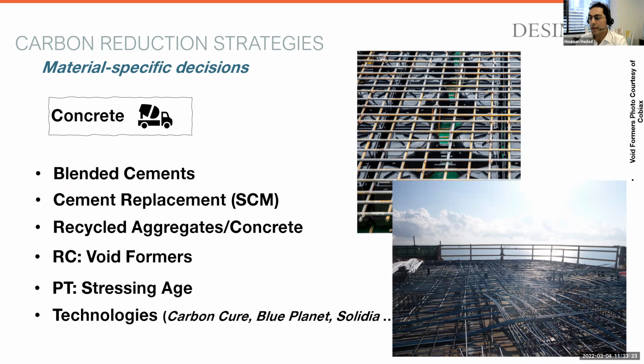Why? Because when you're adding fly ash and slag, chances are that you cannot gain early strength, 3-day, 6-day, 7-day strength in your concrete, and you have to wait a little bit longer. It's more challenging to gain early strength with a high percentage of replacement of SCMs. So it can be used up to, I think, 75% in an element like a foundation. Why? Because the foundation, you design it, you pour it today, that foundation is not going to see its design load until the structure is topped off, essentially, right? And that might take 8 months to 1 year. So you can specify a concrete that gains strength in 120 days, in 90 days, and there's no problem with that.